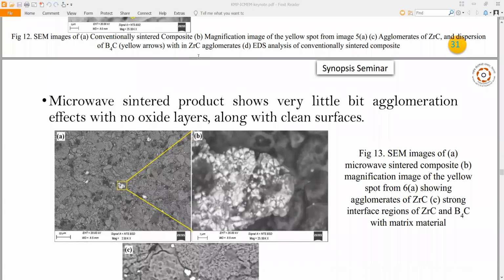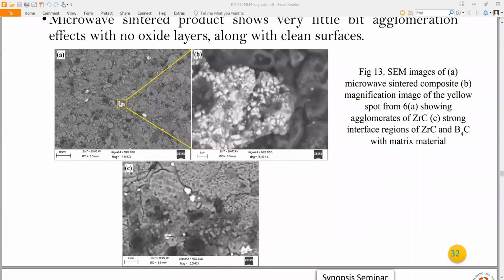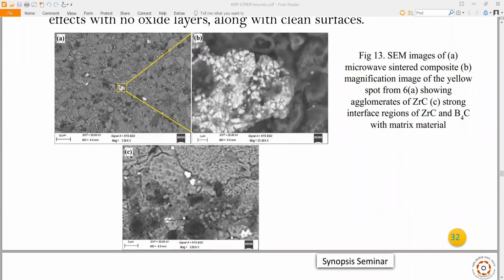Then we are coming to the topic: microwave sintered product shows very little agglomeration effect with no oxide layers along with clean surfaces. We can see it from the figure. This is figure 13, and the same images of A, microwave sintered composite, B, magnification image of the yellow spot from 6A showing agglomerates of ZrC, C, strong interface regions of ZrC and B4C with matrix material.